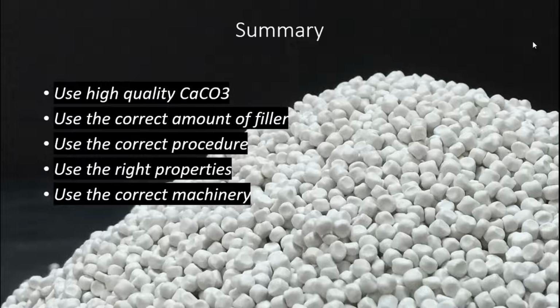So it's really important to use the right properties of the calcium carbonate, because if, let's say, your calcium carbonate doesn't have the lowest amount of impurities, it will cause issues while you're passing it through the extruder, and it will cause contamination in the film. And if you're not using the right whiteness of the calcium carbonate, you'll be getting films that are not white enough and that are yellower in appearance, and it will also reduce the overall value of your product.